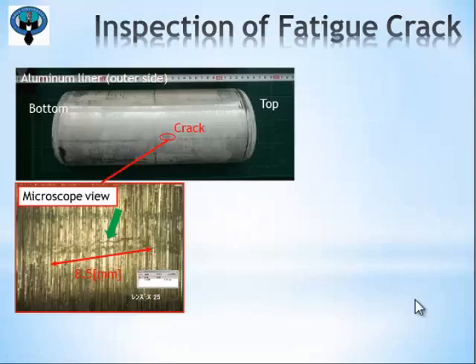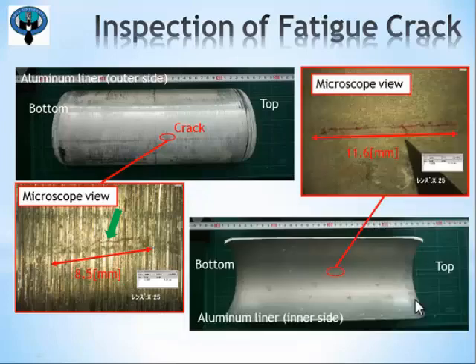After experiment, the aluminum liner and CFRP layer of the examined composite vessel were separated. Above photograph shows outer side view of the aluminum liner. As a result of inspection on penetrations, the fatigue crack was found at this location. Below photograph shows microscope view of identified fatigue crack. These photographs show inner side view of the found fatigue crack. Excluding this crack, no fatigue cracks can be found, as well as no characteristic patterns are found in the base images of other cameras.